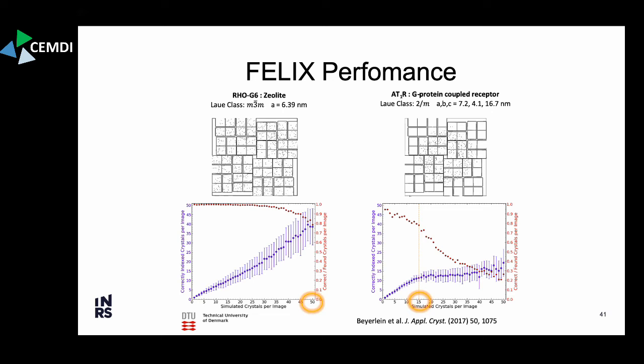And we can see that down here we have the correctly indexed crystals per image versus the simulated crystals per image. So we're able to, all right, let me back up a second here. In order to produce this graph, I ran many of these simulations. So I created a large data set of different simulated diffraction patterns. And then I fed all of those into the algorithm, and I knew the orientations of the crystals ahead of time. So then I could compare what the algorithm produced versus what I knew the answer to be.